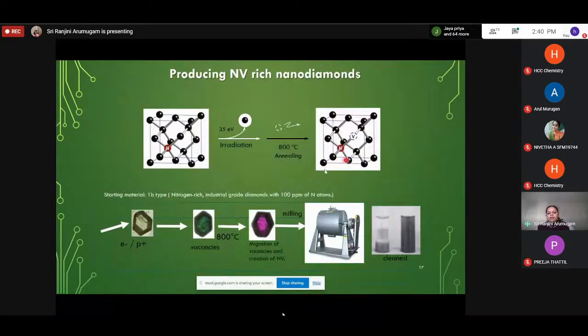So once you have nitrogen-rich diamond, the next step is to create the nitrogen vacancy diamond. So you take the nitrogen-rich diamond and bombard it with irradiation of about 35 electron volts to knock out the adjacent carbon. At this stage, the lattice collapses and is more amorphous than a very perfect lattice. And then we anneal to 800 degrees centigrade in order to recreate the bonds and the lattice, which will form the nitrogen vacancy center.